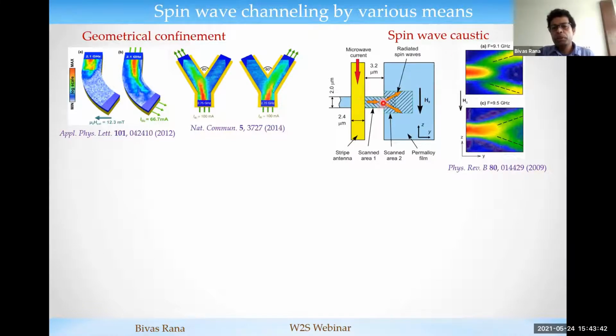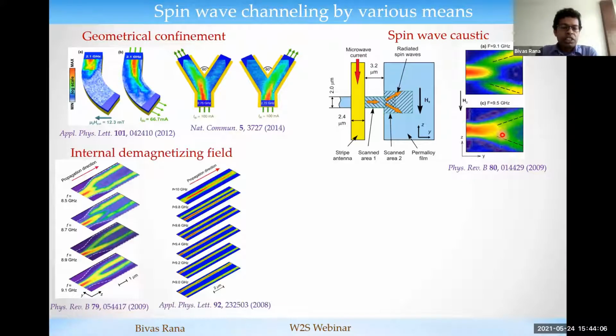The next way is by using spin wave caustics. When the spin wave enters from a narrow waveguide to a wider waveguide, the spin waves do not go in a straight line. Okay, they are bent like this because of the anisotropic nature of the dipole interaction. So just by changing the orientation of the magnetic field, you can steer the direction of the spin wave like this. Okay, the third method is confining the spin wave at the demagnetized area, because at the edge of the waveguide, there are demagnetized areas where the effective field is smaller than the effective field at the center. That means if you change the frequency of the spin wave, the higher frequency spin waves are confined at the central area, whereas the lower frequency ones are confined at the edge area.